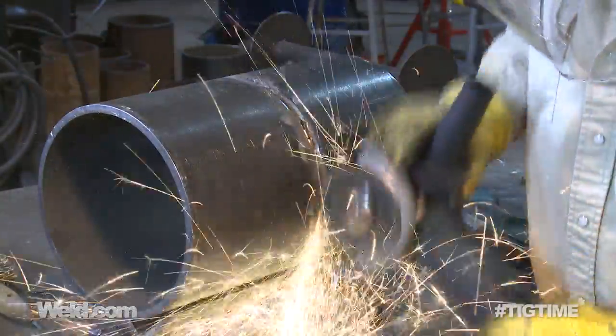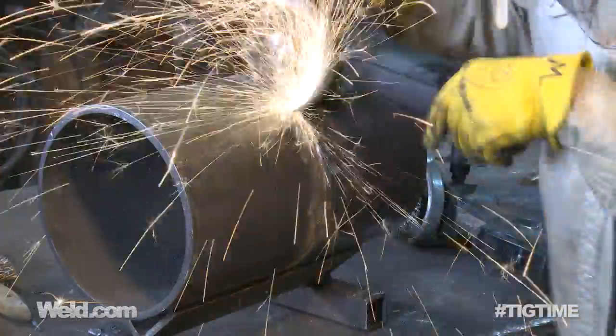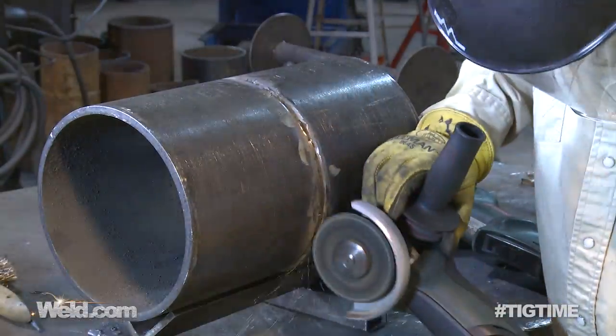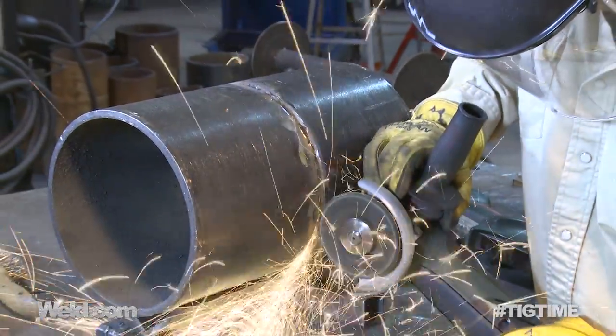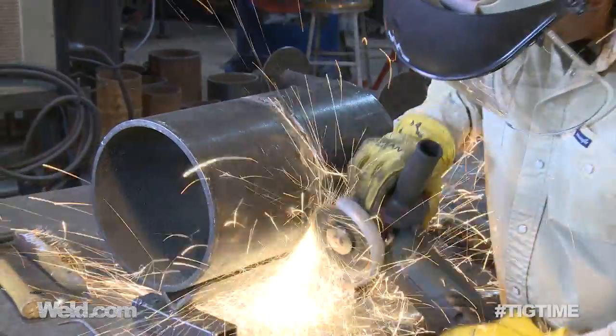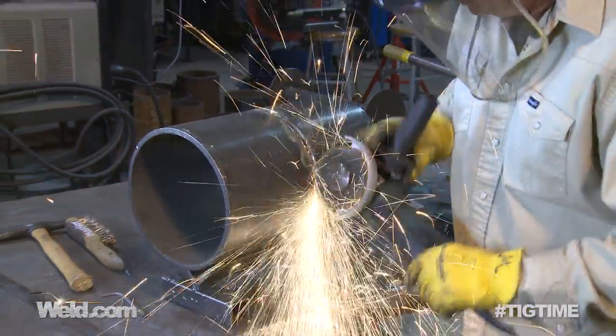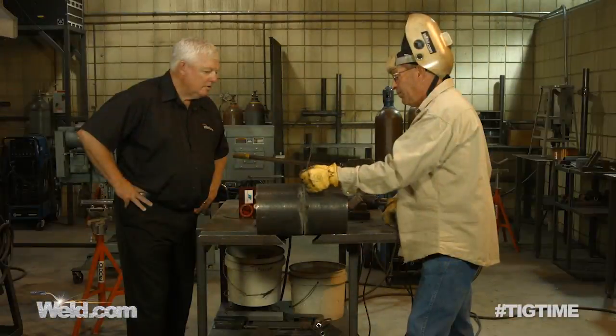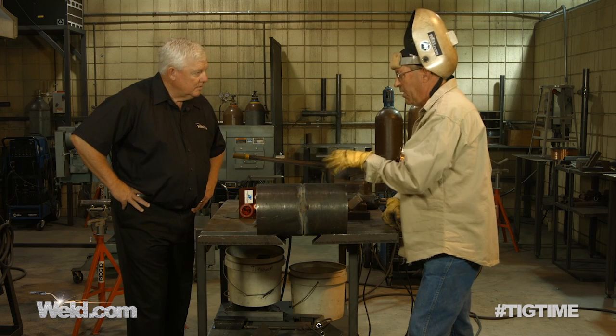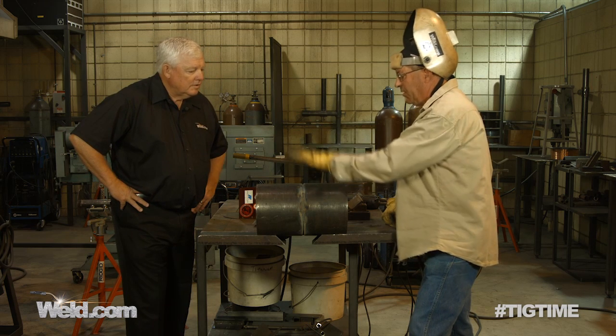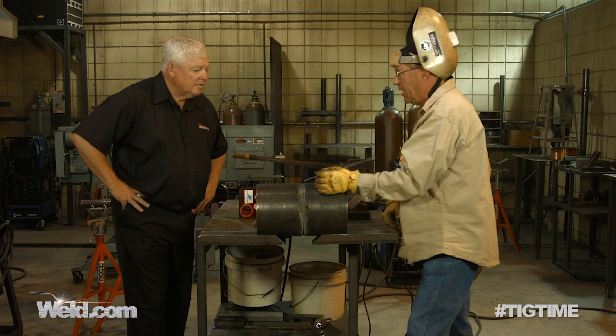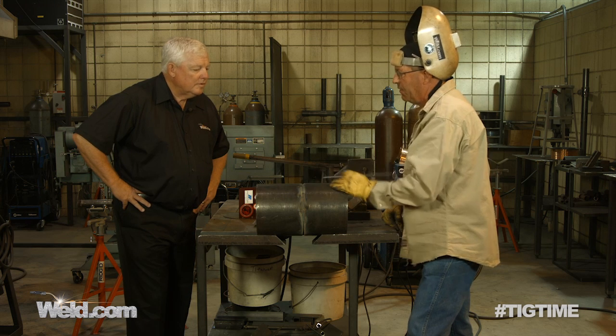But what I don't like doing is grinding all the way down to pure white metal. I don't think there's a need for it when you're welding with 6010. That's why we run a hot pass. We increase our amperage, and we use a technique where we lift the arc a little bit, and the increased voltage helps blow this stuff. The hot pass is just digging the slag out that's left behind on either side of the root.